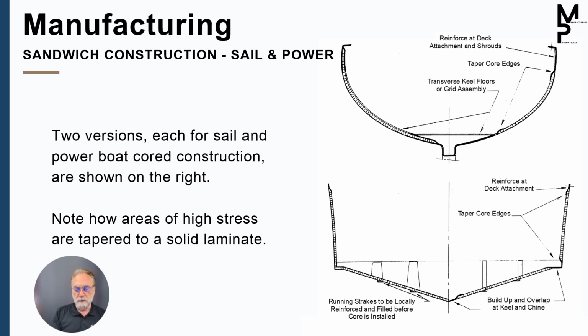Now, if you think about what core is for, it's for bending. And the keel actually forms a stiffened point, as do our stringers and our chine. So all of our bending loads are maximum in between these supports. As we move very close to the edge, we don't really need a core for bending loads. And in fact, by putting it here, we put a very large stress riser, which means we're going to have to make this area very, very strong because it's very stiff and it's going to attract load.